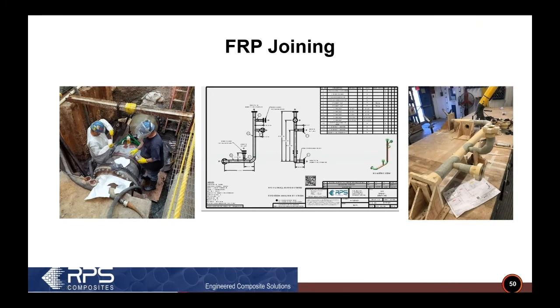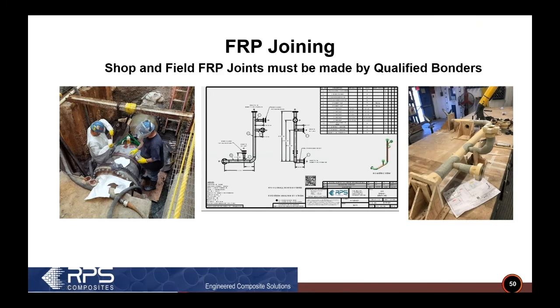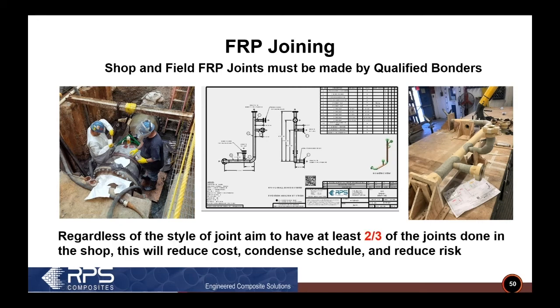When it comes to joining FRP, really the takeaway here is that both the shop and the field joints need to be made by a qualified bonder. Just like if you're doing metallic pipe and someone has a welding ticket or is a qualified pipe fitter, it's the same in FRP. You have to be qualified to do the joints. What we usually like to see is to have about 2/3 of the joints done in the shop and maybe leave about 1/3 of the joints done in the field.